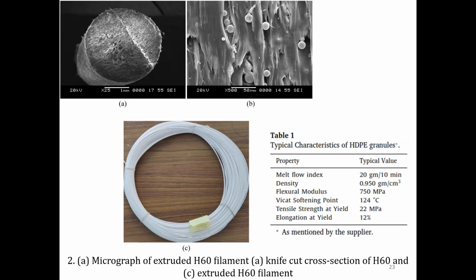In a single screw extruder, they come with either 3 heating zones or 4 heating zones. So you need to maintain appropriate temperature, and when I say appropriate temperature, you need to really bother about the glass transition, melting, and degradation temperature. As per that, you set it properly. You set the takeoff speed and the screw speed to have either a 2.85 or 1.75 plus minus 50 micron diameter. Please do remember why I'm stressing again and again on plus minus 50 microns: it is the requirement for a 3D printer. If there is a variation in this, you will have non-uniform deposits when you print. The nozzle gets clogged because of the overflow of the material.